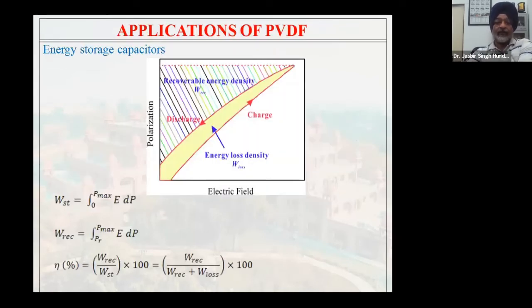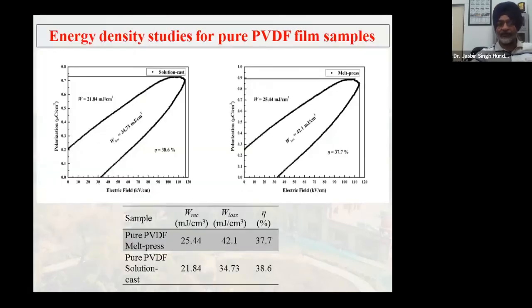Actually, we are trying to study this energy storage. We are trying to study these PVDF BCZT composite films for energy storage devices. This is just a part of the hysteresis loop you see here. From here, we can find out the energy loss density while charging and while discharging of the film. So you know the recoverable energy density and the area under the loop. By comparing, you are able to find out other parameters. This is the thing which we have just reported in a research paper.